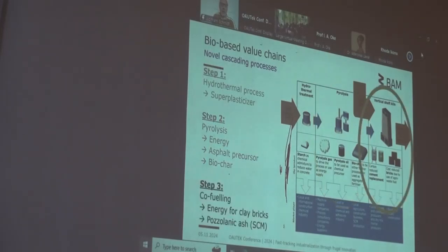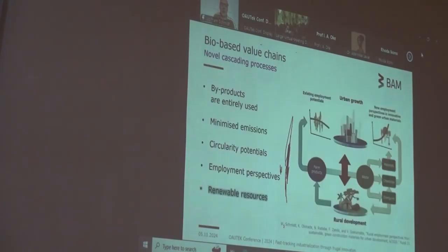And finally, if the biochar is rich in silica, we burn it together with bricks so that we have the energy to produce the bricks. What comes out after this process is an ash which has pozzolanic properties and can help to reduce the cement and concrete. This way we use the byproducts entirely, we minimize the carbon emissions, we create circularity potentials, we create employment perspectives, particularly in the rural areas, based on construction materials which are used for the urban growth. So that's a perfect synergy.